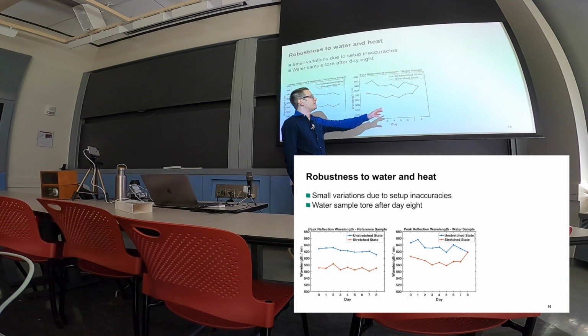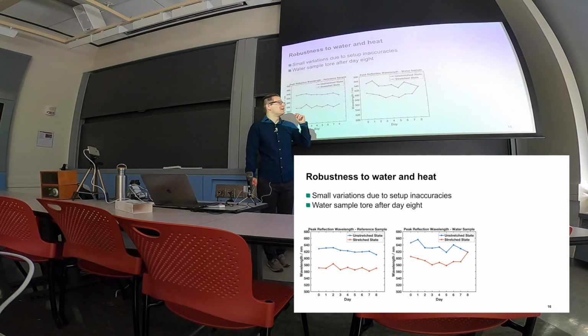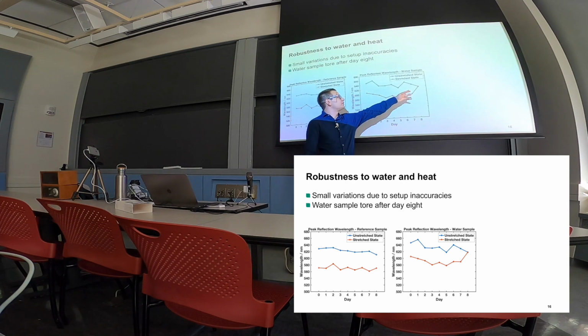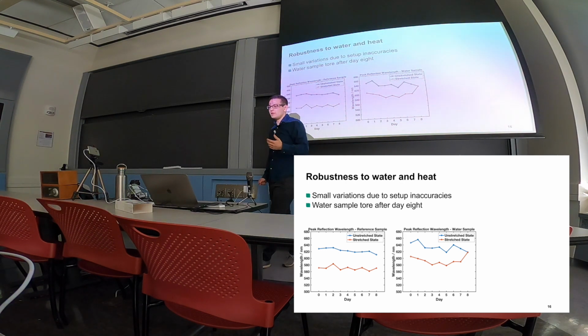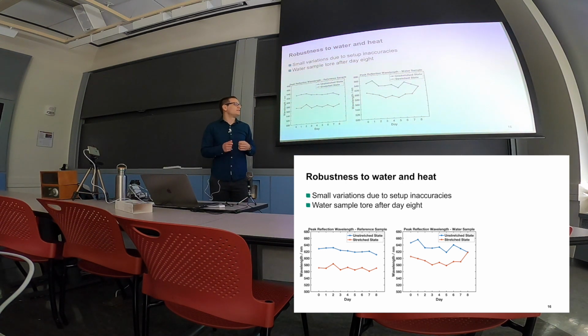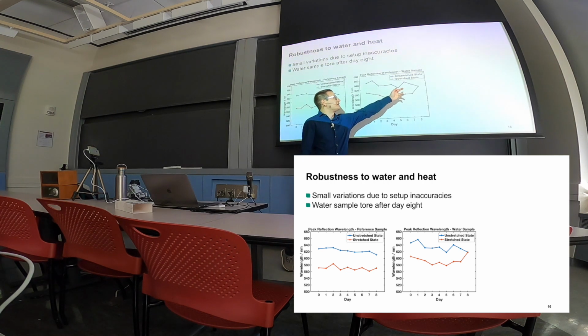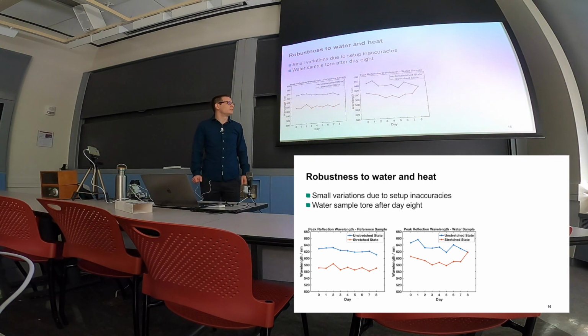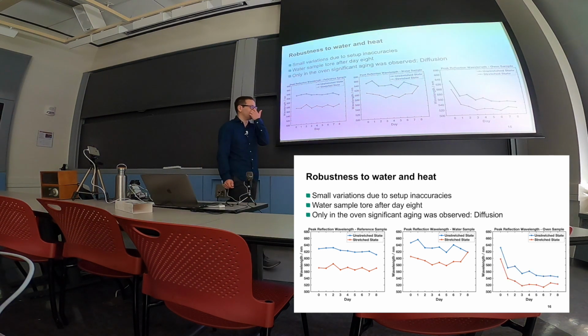The only thing that I noticed is that after 8 days, and this is also why I stopped the measurement after 8 days, the peak wavelengths in the stretched and unstretched state have been the same, and the reason for that is that the sample tore when being stretched after the 8th day. So one can say that the mechanical stability of the sample had problems with being in water, but the peak wavelength was not a problem, so aging of the photopolymer was not a problem.